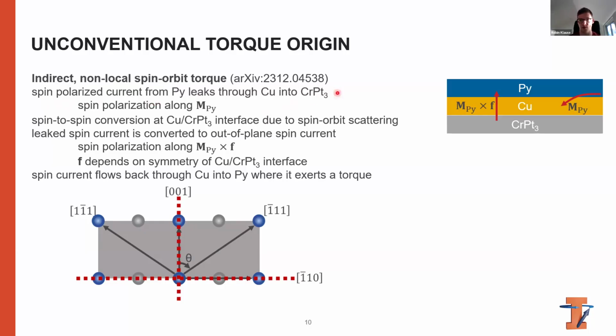So there's a current that flows also through the permalloy, which we apply with the RF current, and that leaks through the copper and CrPt3 to this Cu/CrPt3 interface. And the spin polarization of this is along the magnetization direction of the permalloy.